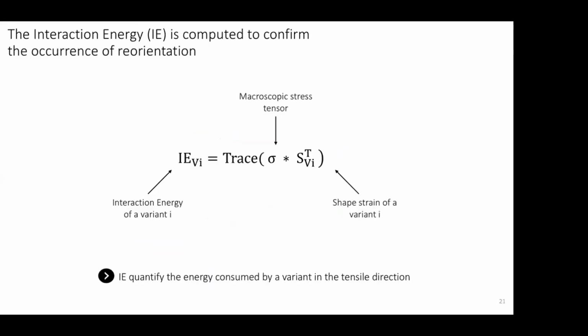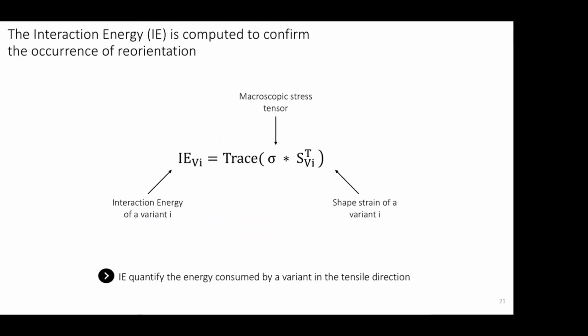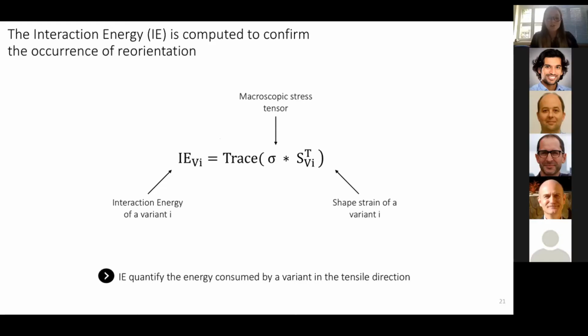But to be completely sure that we have reorientation, we wanted to compute a value called the interaction energy, because in shape memory alloys, generally, when you have a martensite that can induce reorientation, the variants that can grow at the expense of the others are the ones that maximize the value. I don't know if I was very clear about it. When you have reorientation, you have several variants, and 1 variant can grow at the expense of the others under the effect of deformation. And if you compute the interaction energy, the variant that maximizes this value should be the one that grows at the expense of the others. So we want to check if it works in our case.